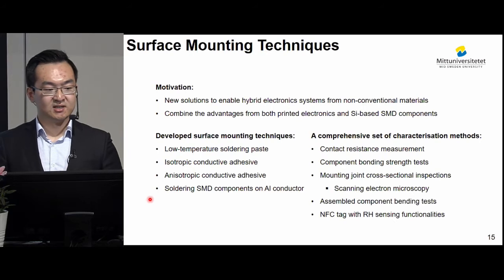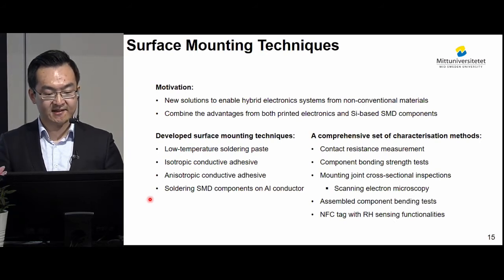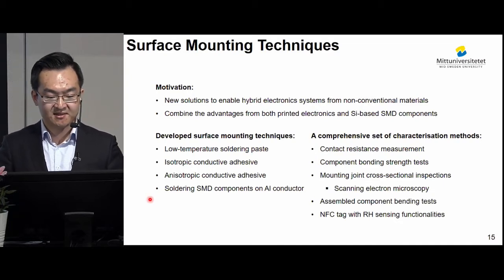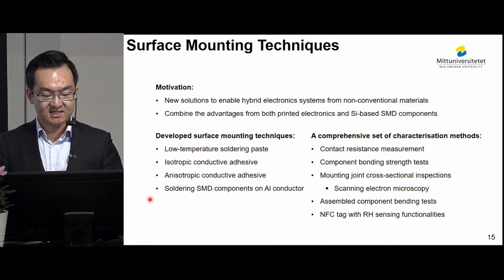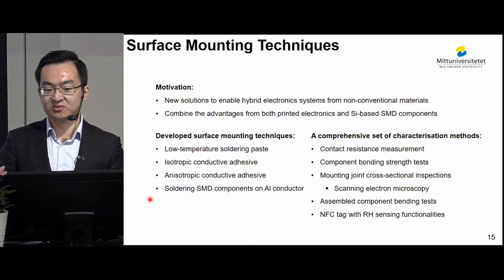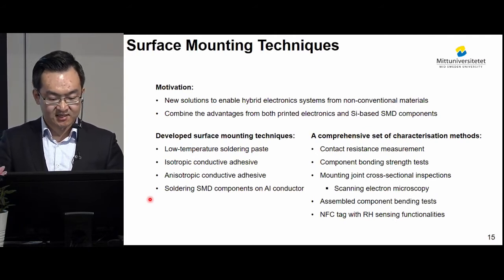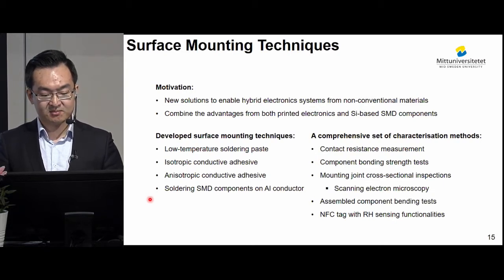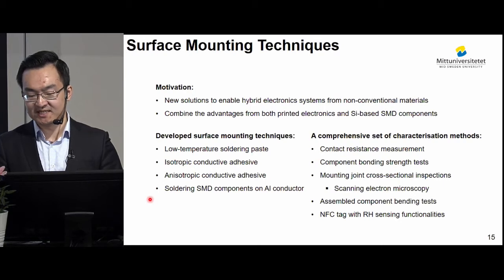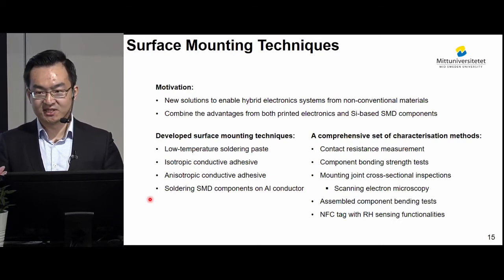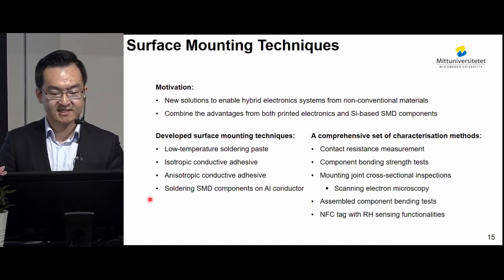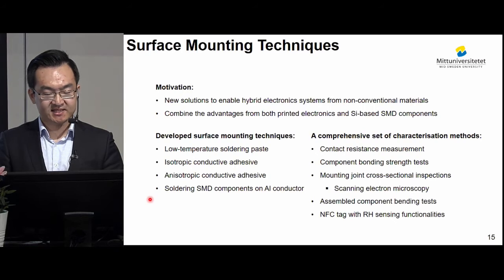In addition to the surface mounting techniques, we also came up with a comprehensive set of characterization methods where we measure the contact resistance, component bonding strength, and we inspect the cross sections of the mounting joints using scanning electron microscopy. And we also did assembled component bending tests to study if the assembled circuits are suitable for systems that require bending. And in order to show that the surface mounting techniques and flexible circuits can be used in forming functional electronic systems, we implemented NFC tags with relative humidity sensing functionalities.